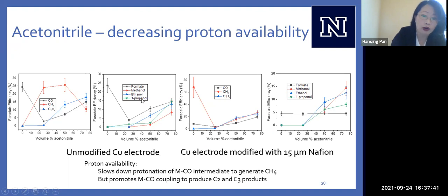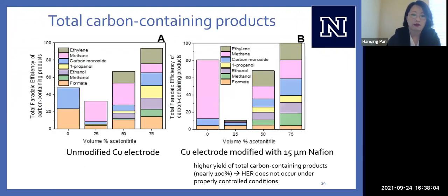We're making propanol. So this set of experiments is confirming our hypothesis that by decreasing proton availability, we're no longer protonating that CO intermediate to make high amounts of methane. We're instead pushing those CO intermediates towards each other for them to dimerize, trimerize to make these multiple carbon products. So we can add up all of our carbon containing products, excluding hydrogen, and we hope that it can add up to 100. We're able to achieve that with a copper electrode modified with Nafion.